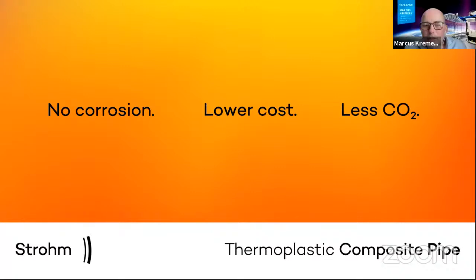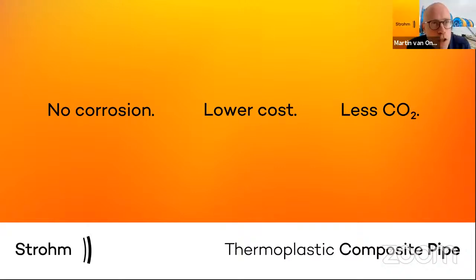Yeah, and these numbers are all design pressures. So the pipe can have more than the design pressure. So I believe it's up to around 2,000 bar or something. Yes, it's around a factor of 3.5, typically 3.5, sometimes even 4. So an example of a system we just supplied to Shell in the US was rated at 10,000 psi, so 690 bar, but the burst level was around 3,000 bar. So that is quite significantly above the design pressure.